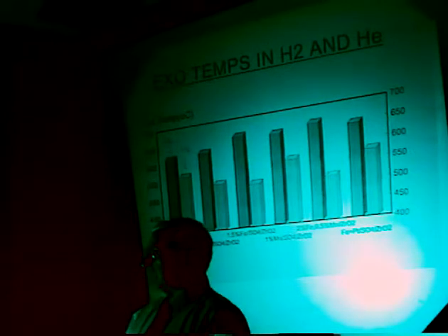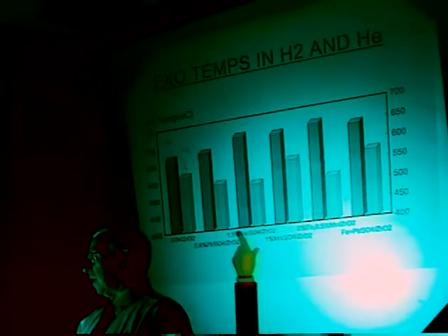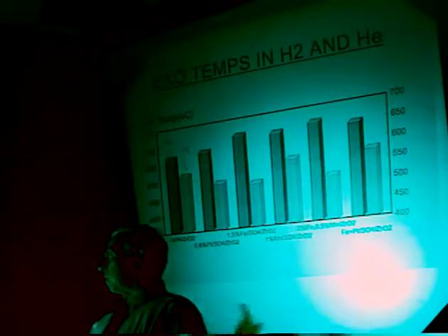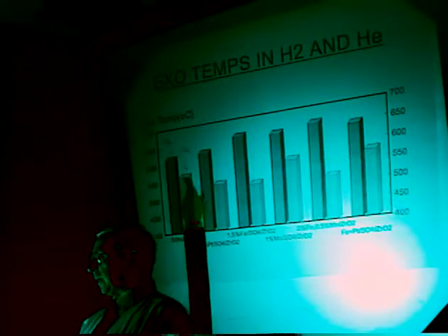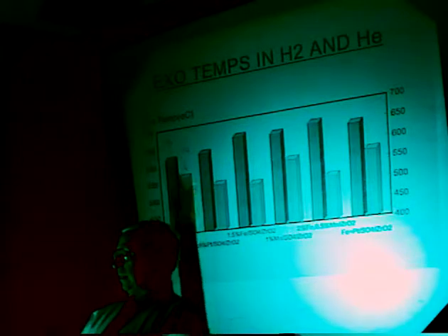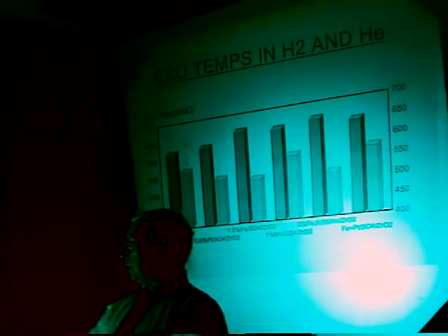If you look at the exotherm in air or helium, it has little influence on whether you have platinum or iron manganese as is used as promoters. If you carry out the treatment in hydrogen in contrast to air or helium, invariably the exotherm is 100 to 150 degrees lower, and you lose the sulfur as H2S rather than oxide of sulfur.